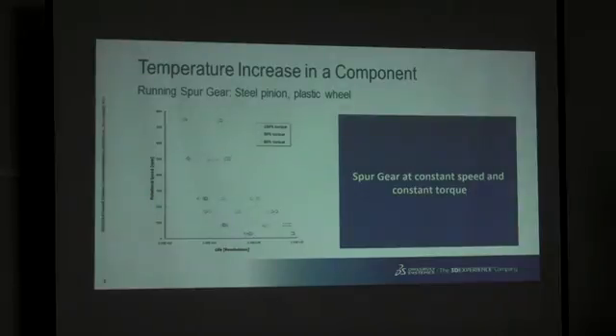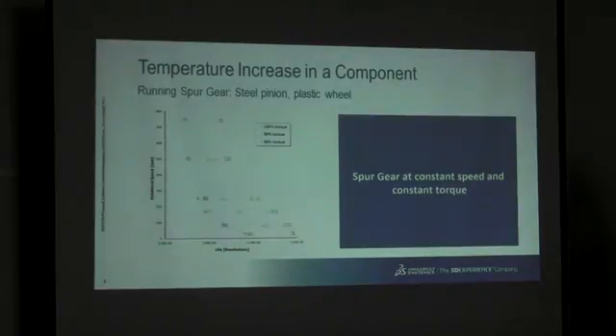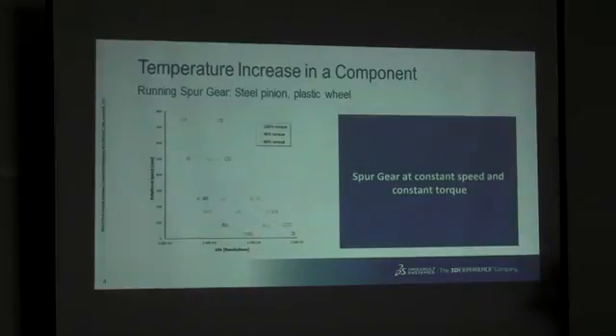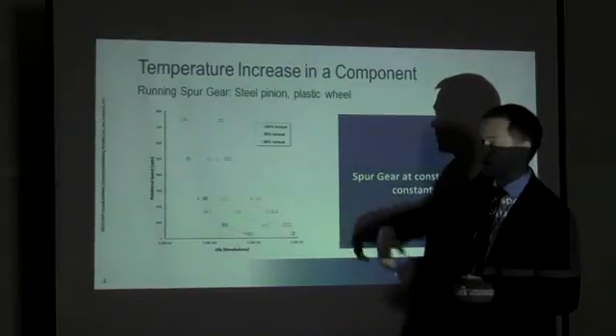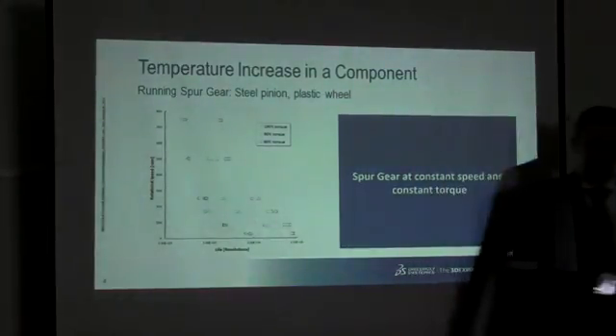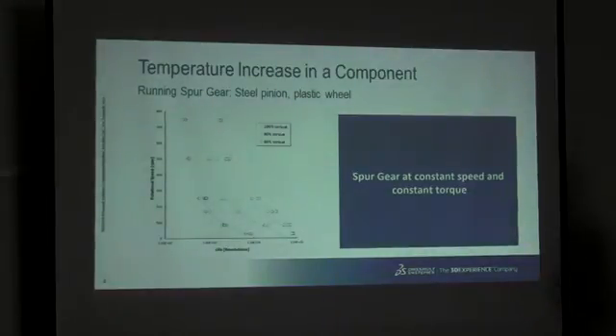Now that's a specimen. That's one thing. But we have components, so we need to think a bit further. These are investigations that were conducted on a running spur gear with a steel pinion and a plastic wheel. And the investigation was simply to see what happens when we reduce or increase the torque. So in this case, 100% is a maximized normalized torque. And what you can see here is with the rotational speed, with increasing rotational speed, obviously the life becomes much, much shorter.